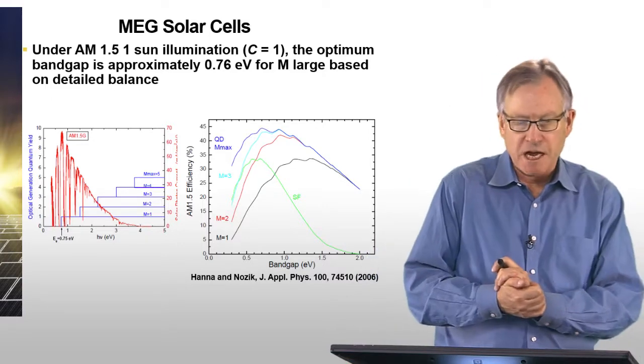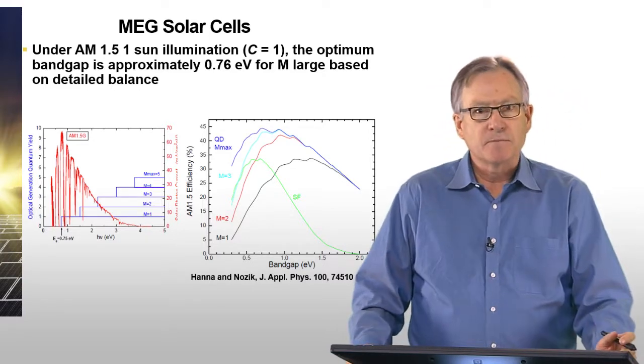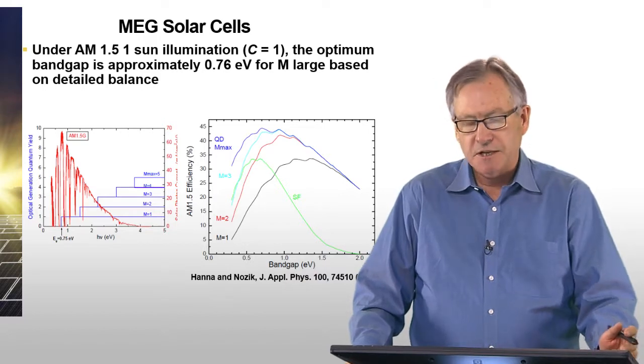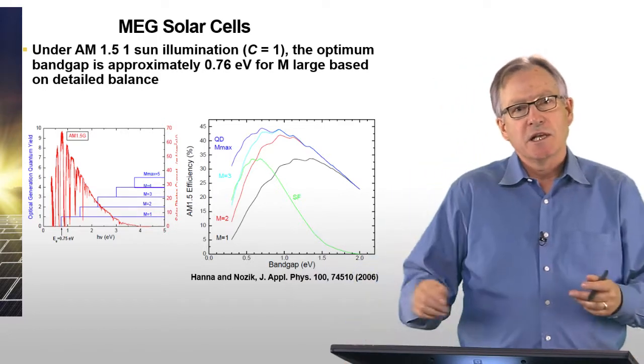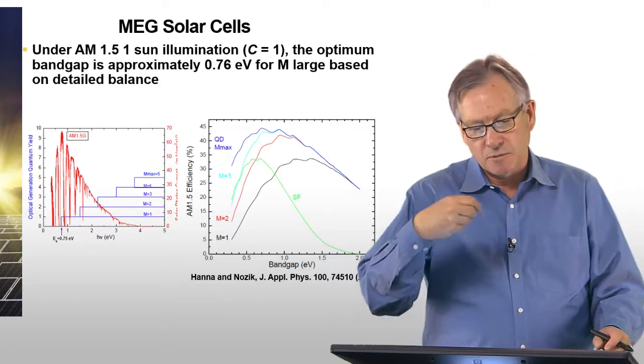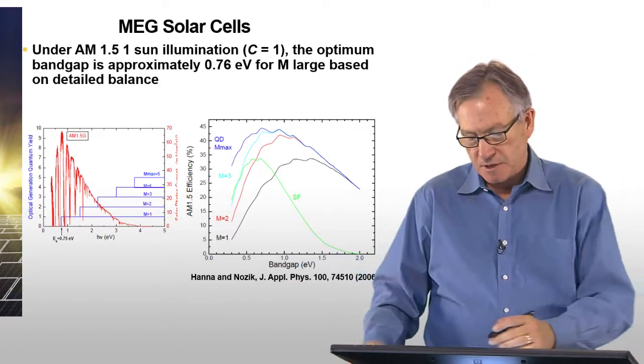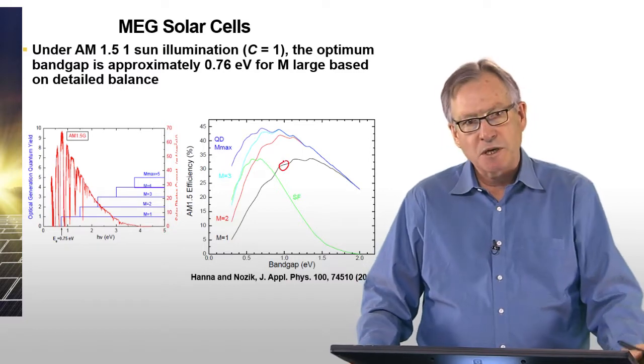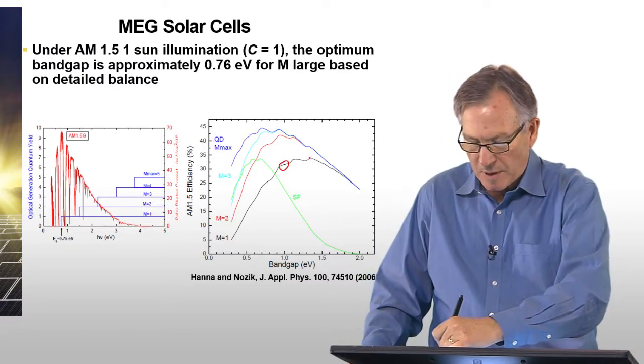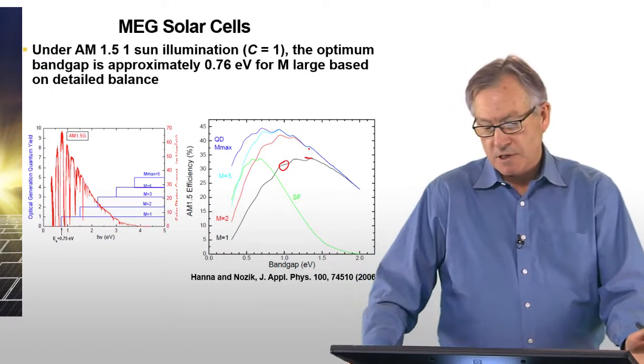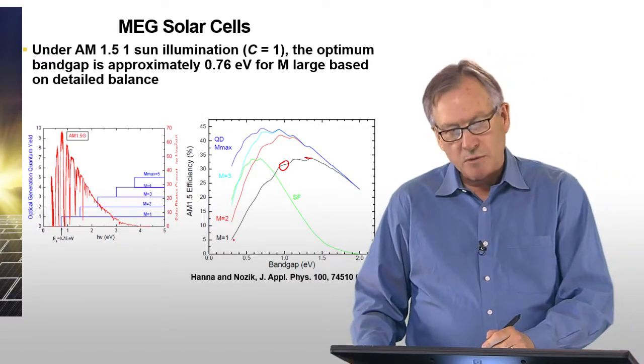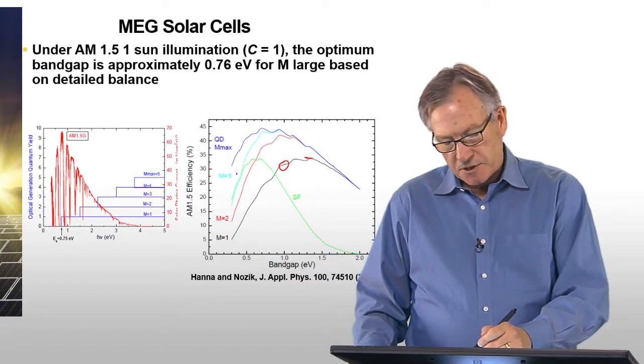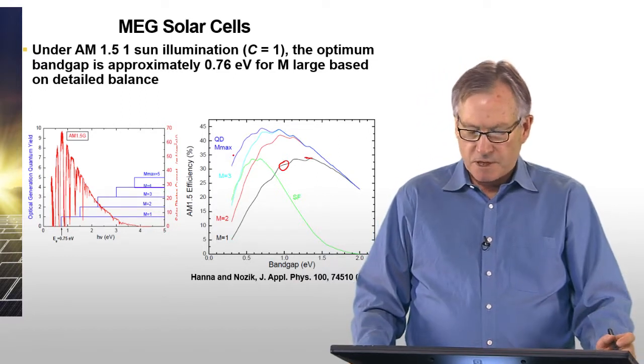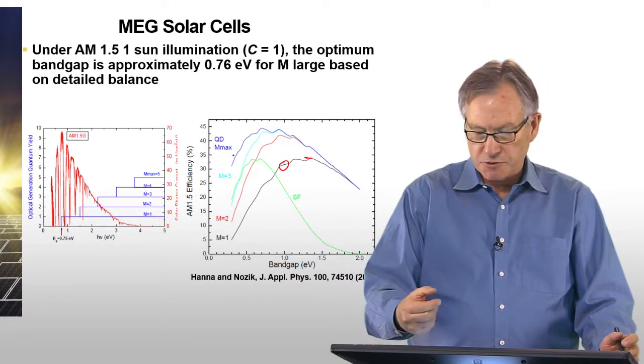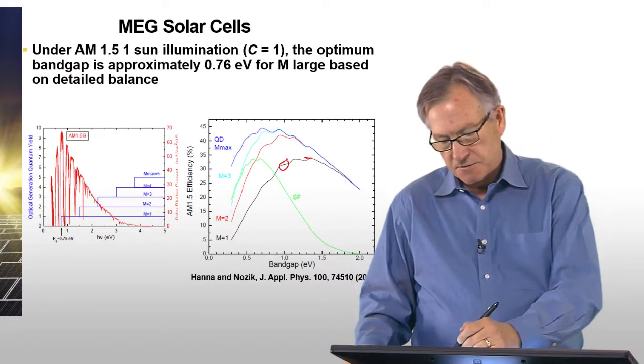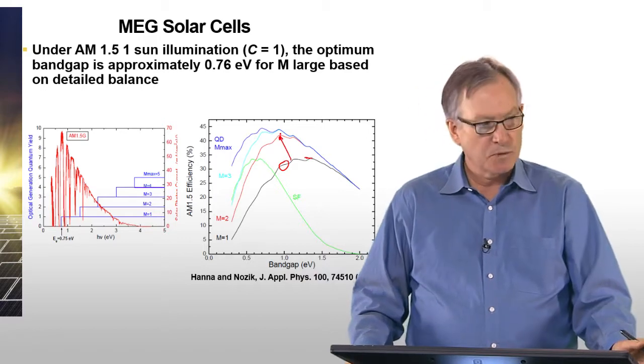This just shows the calculation of the detailed balance efficiency that I talked about before, the Shockley-Queisser calculation, modified for the effect of multi-carrier or multi-exciton generation. What's shown in this curve is basically the Shockley-Queisser curve I showed before, which has a maximum of about 33.7%. So this is assuming no multi-exciton generation. And now if you put in different thresholds, if you assume that electrons at twice the band gap can produce an additional electron hole pair, this efficiency moves up quite a bit. As you can see, it moves up to be over 40%.